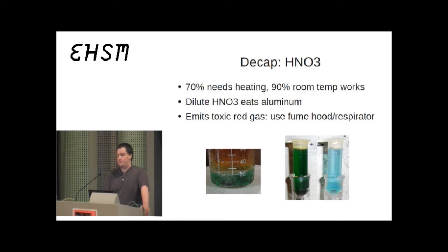This is the same chip in both these vials, and I put them in there at room temperature, one with some white fuming nitric acid, the other with 70%. I could actually visually see the chip disintegrating on the left as soon as I put it in. Well, the one on the right, this is after about 24 hours, but I don't think it changed much after about an hour, only the leads had basically been eaten and the epoxy, the chip number was still readable. So even just a little bit higher concentration has a profound effect.